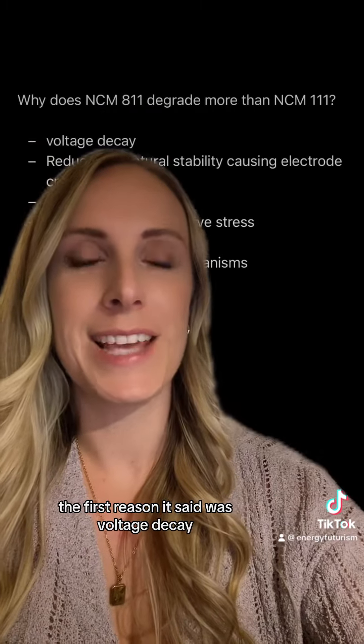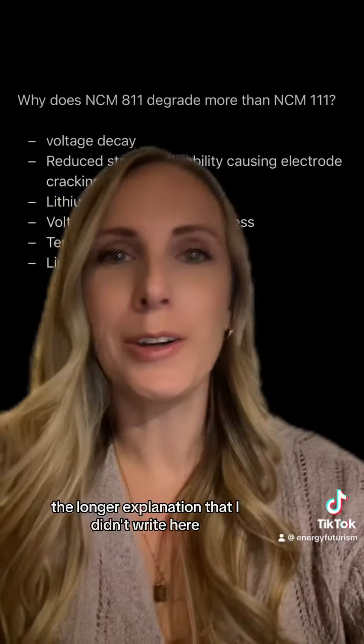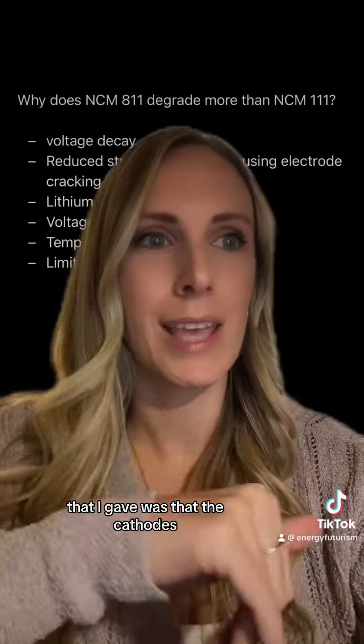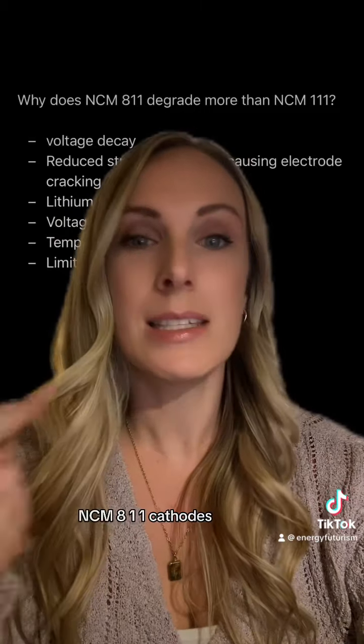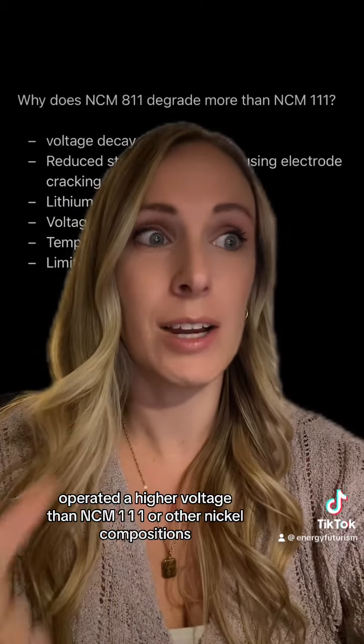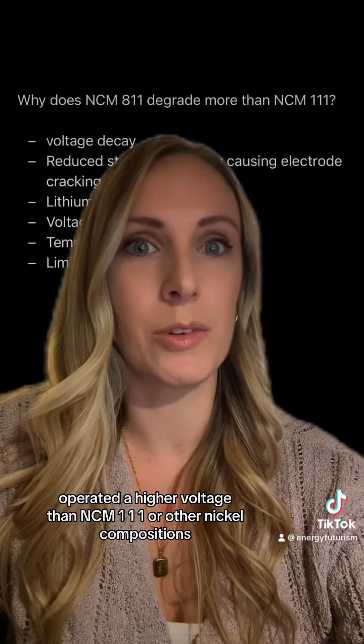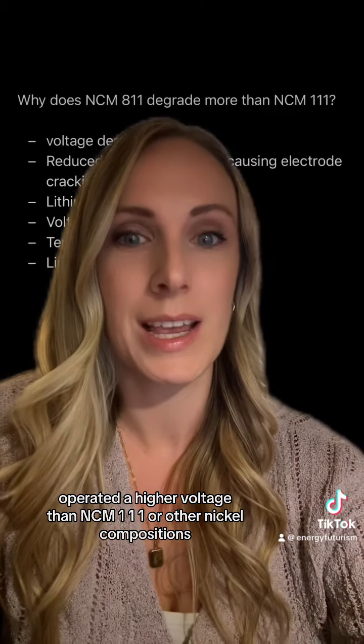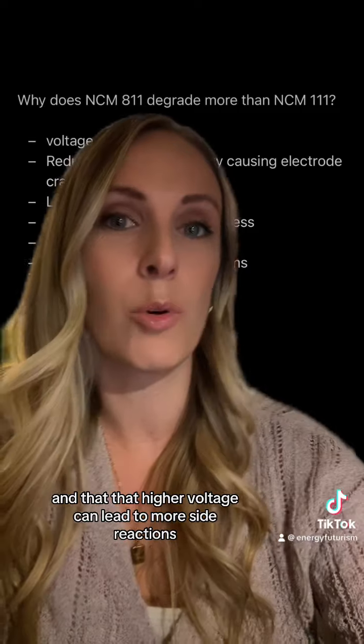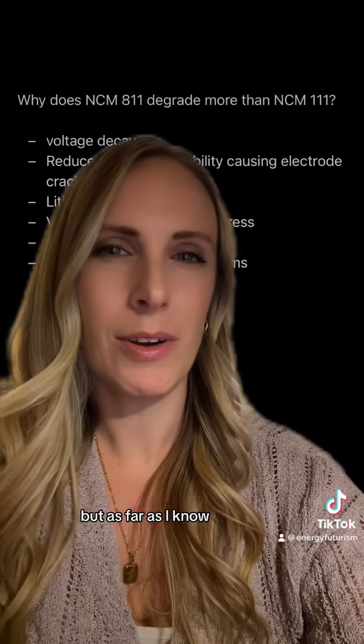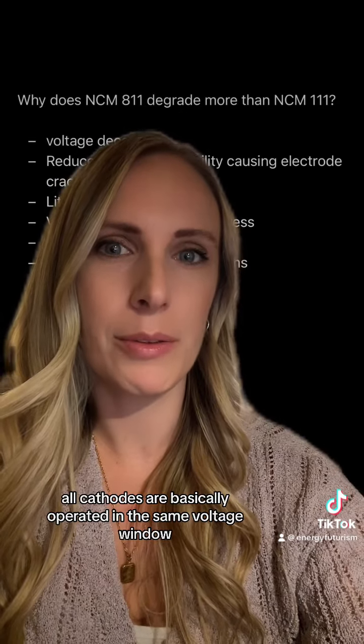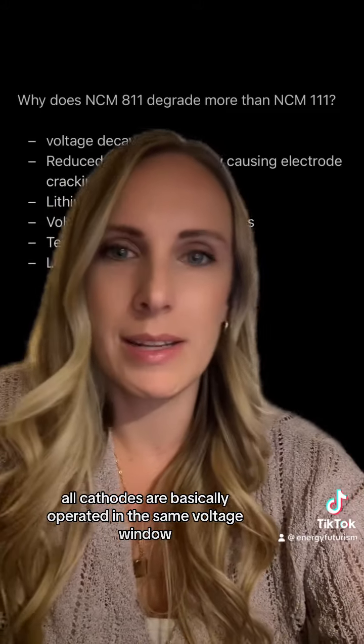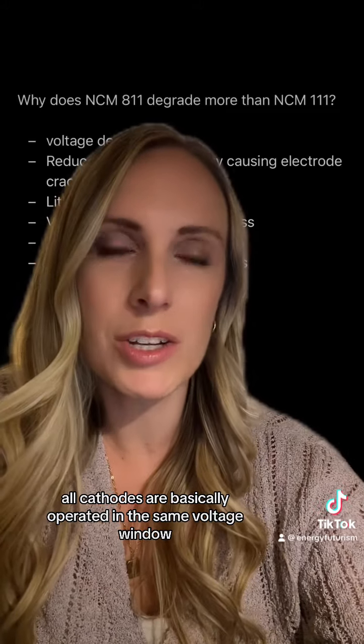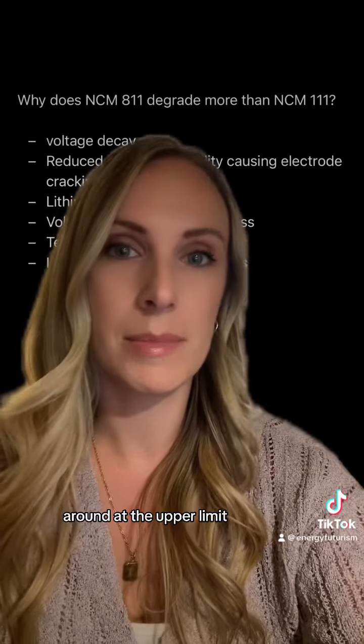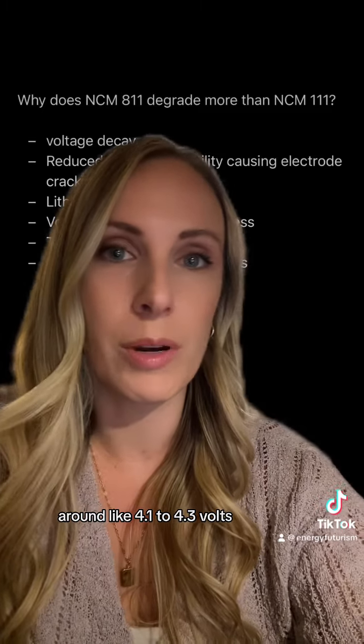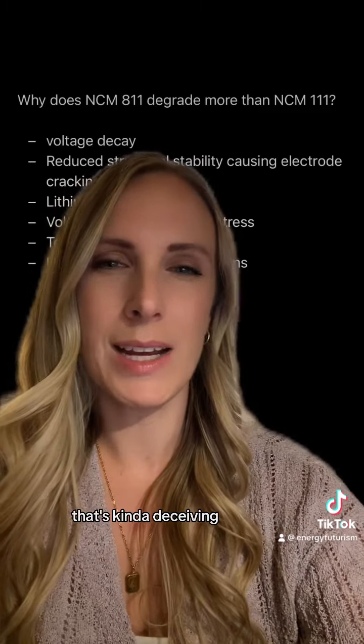The first reason it said was voltage decay. The longer explanation that I didn't write here was that NCM811 cathodes operate at a higher voltage than NCM111 or other nickel compositions, and that higher voltage can lead to more side reactions. But as far as I know, all cathodes are basically operated in the same voltage window, with an upper limit around 4.1 to 4.3 volts. So that's kind of deceiving.